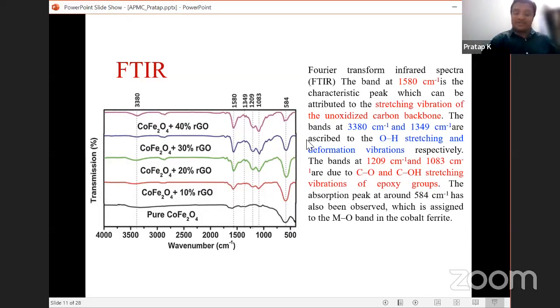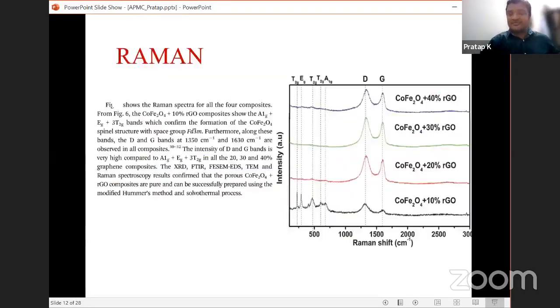So using all these techniques, we have confirmed that cobalt ferrite is exactly formed. But how do you confirm the graphene? You confirm graphene only by Raman spectroscopy. In the Raman spectroscopy, if you observe D and G peaks, then only you believe that there is graphene in it. So look at it.